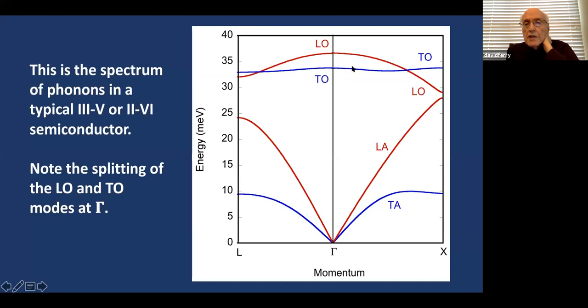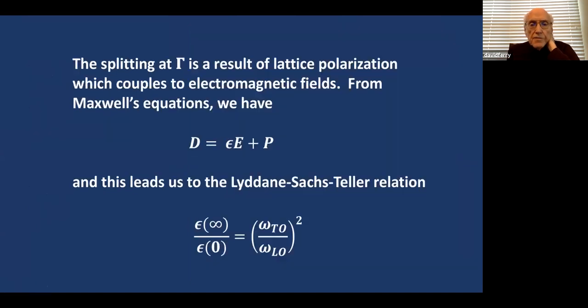Now note this splitting up here. This splitting does not occur in silicon. Okay. But it does occur in compounds, most compound semiconductors like zinc blende. And that's very important because it tells you something about the material. And what it tells you is that the lattice is polarizing in the electromagnetic fields. In other words, there's charge on those 2 atoms that causes a polarization vector in each unit cell.